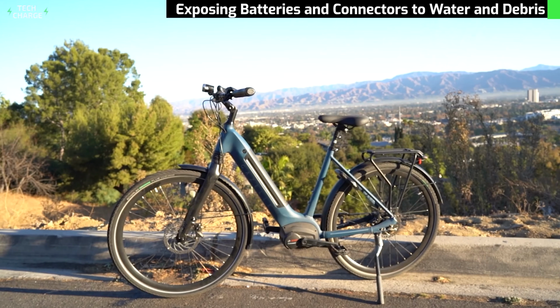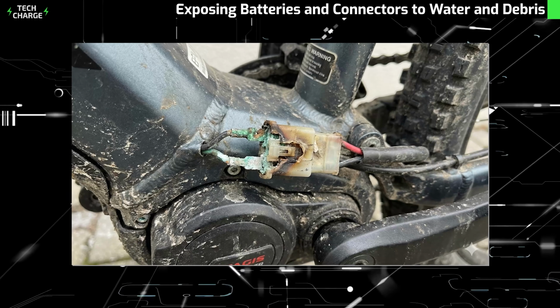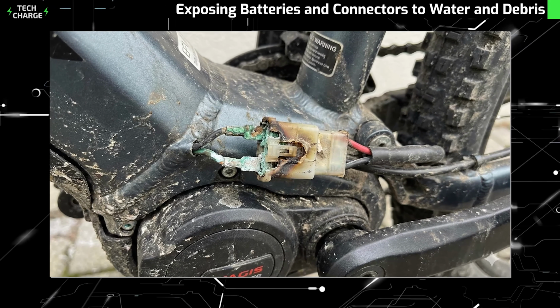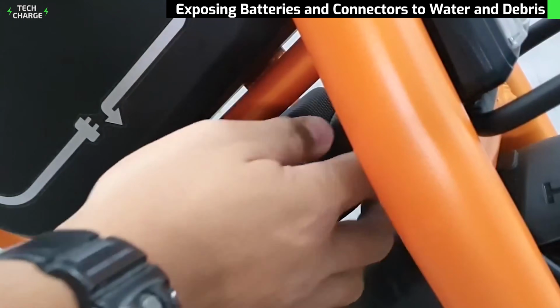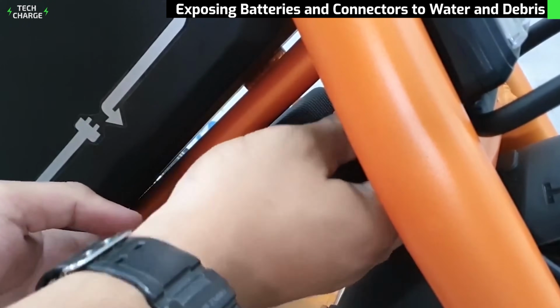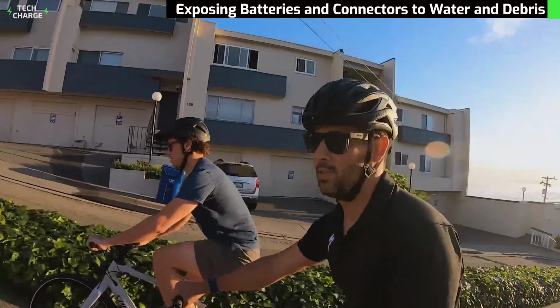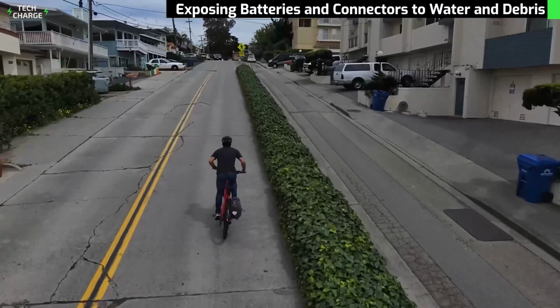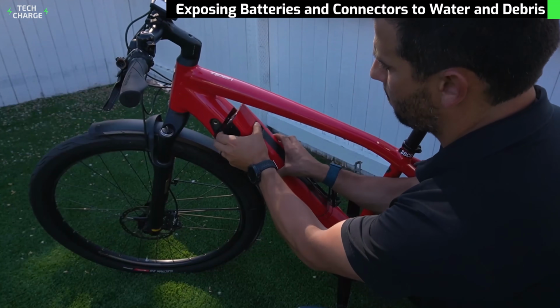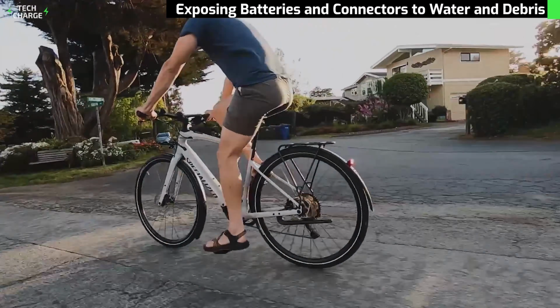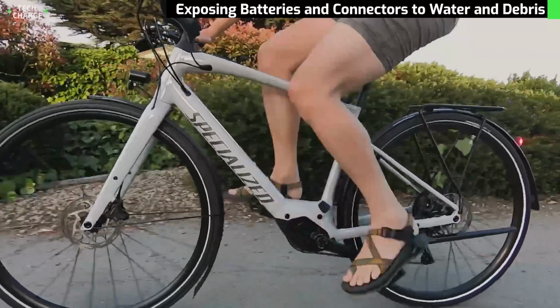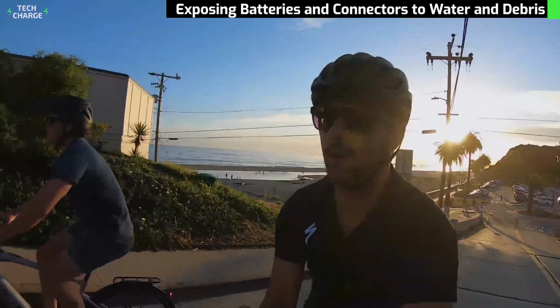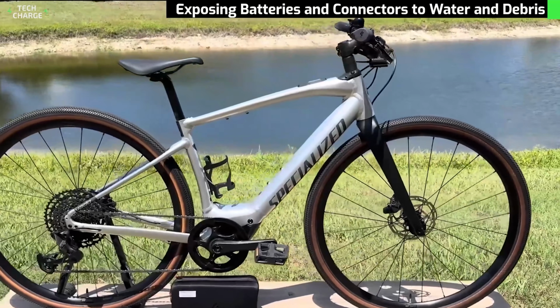Water ingress doesn't always cause immediate problems. Instead, moisture gradually corrodes connection points and creates conductive bridges between components that should remain electrically isolated. Debris can jam into connector pins, creating partial shorts that generate heat during charging or discharge cycles. These slow-building failures can manifest days or weeks after the initial exposure, making it difficult to connect cause and effect.